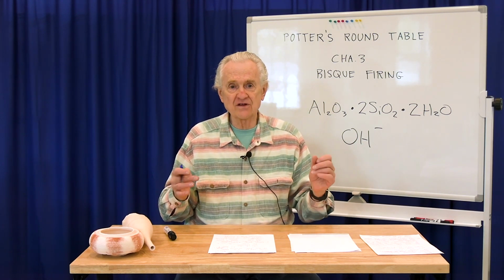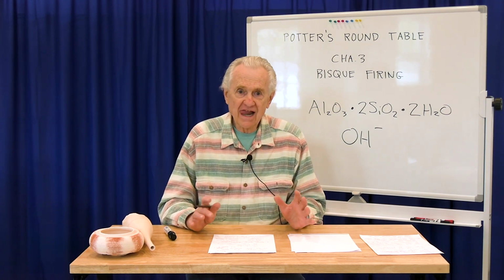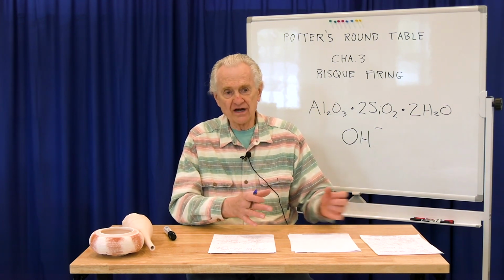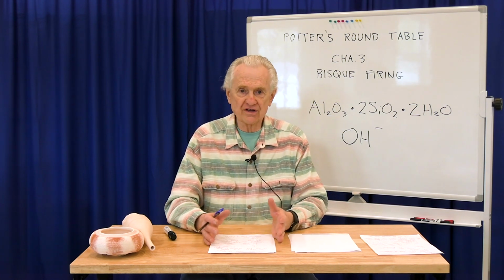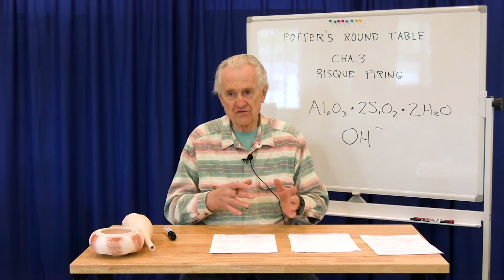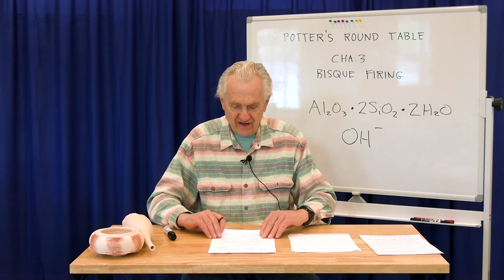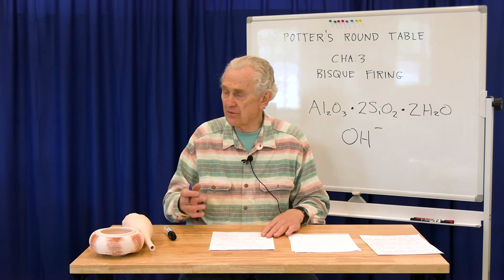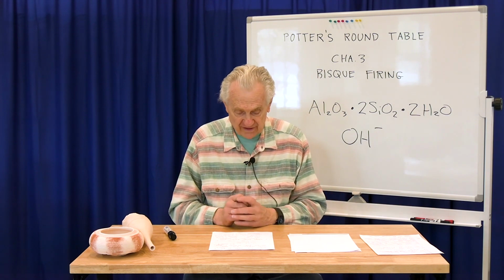Again, even though we talk about how water boils at 212 degrees Fahrenheit, in a small quantity of water in a pot, that's true. But with the structural water and the water contained in the clay, the water does not come off at a specific temperature. It comes out over a range of temperature and a range of times. And besides just the form of the water, there are other factors that can affect how easily the water can be removed from the clay.